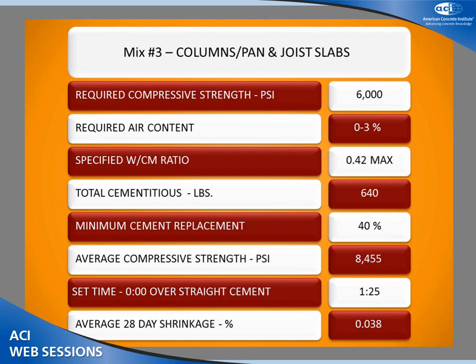And now here we're starting to show set times, because then the flat work is where it becomes relevant. Set times are a big issue when using these high replacement mixes. And I was delighted to see some of the things that Dr. White presented as for ways of accelerating these set times. Here we were at 1 hour and 25 minutes above the set time of straight Portland that had been tested. Not bad, but the finishers, we want to get them home for dinner, and that's a big deal. Time is money. There's a few more. There was a few hours of overtime on this project related to set time, but they were very few.